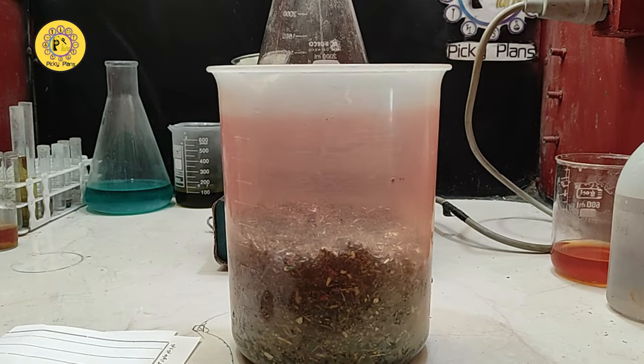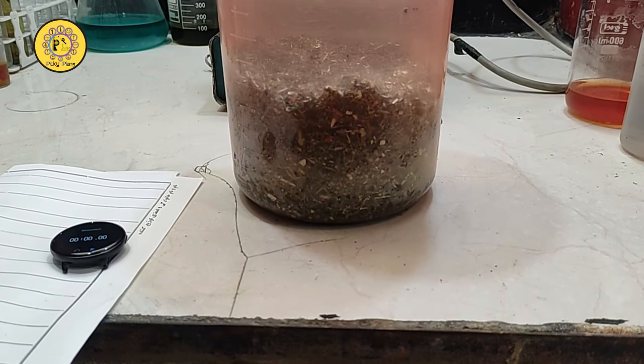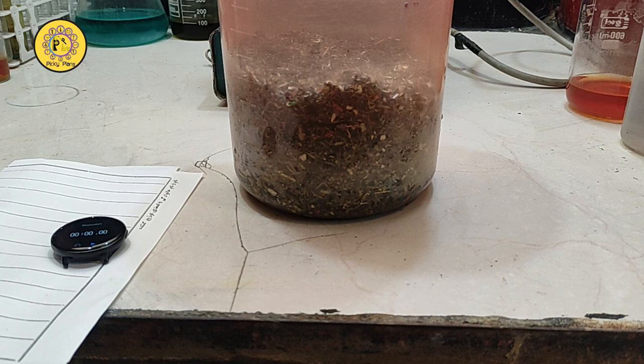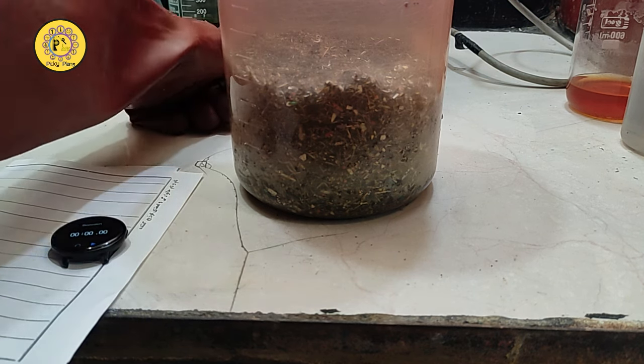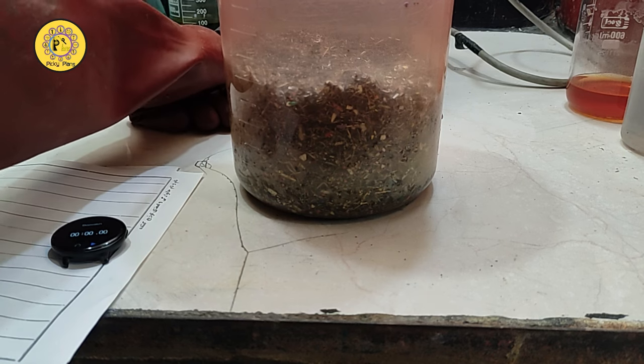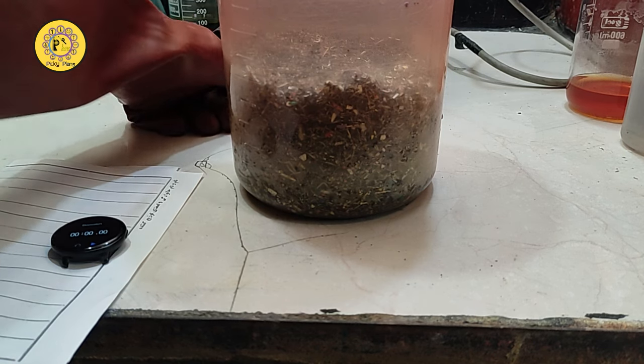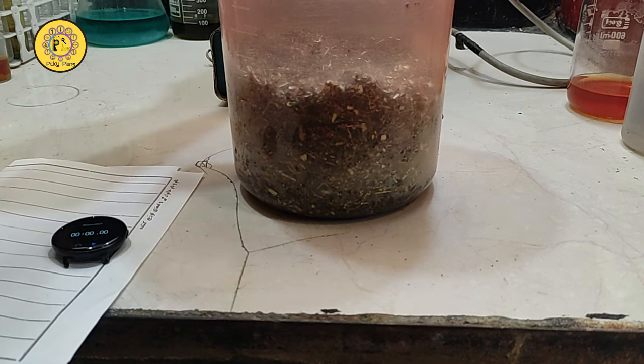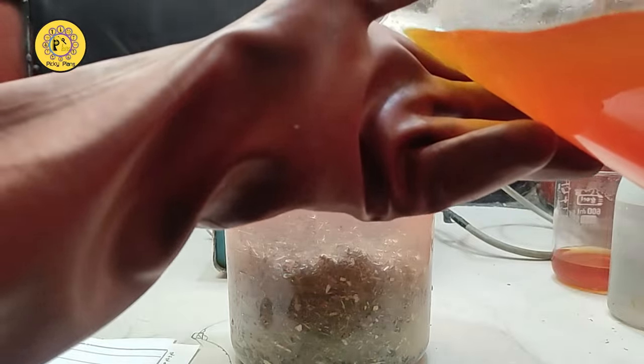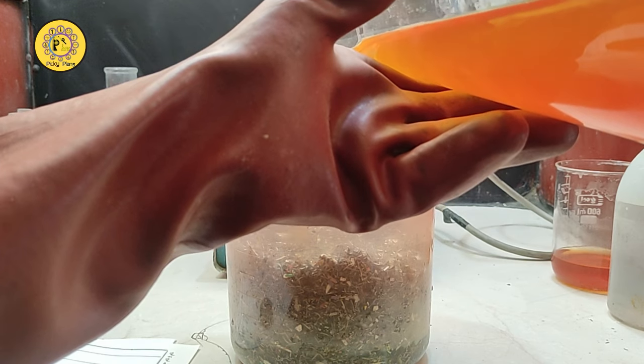After adding the leaching solution to the pins, I'm going to track the time using this stopwatch. Usually for this type of pins, as I did some tests, the pins don't need to sit in the solution for more than 5 minutes. It's usually done in 2 minutes though. Let's see. I add the solution to the pins slowly to not take the precipitated materials out.